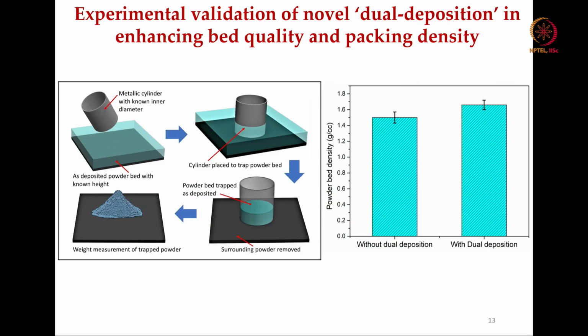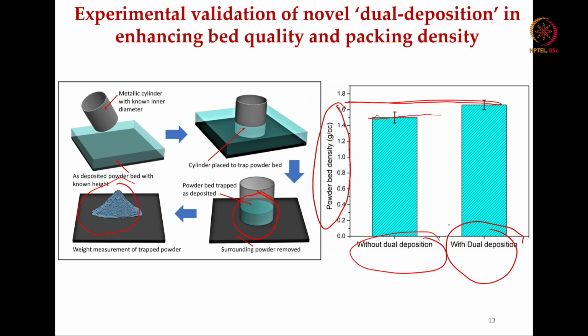After that we have used the dual deposition technique in enhancing the powder bed quality and packing density. If you see the weight measurement of the tapped powder and then the surrounding powder bed method, when we did this powder bed tapping of the as deposited powder and weight measuring of these known quantities, we found out that the powder bed density without dual deposition was a little less. It was like 1.5 and then it increases to 1.8 with dual deposition.